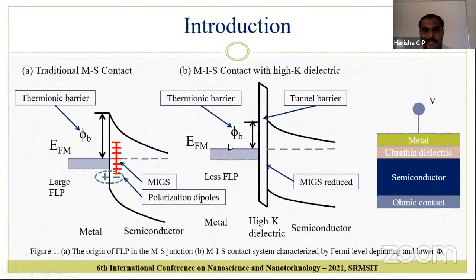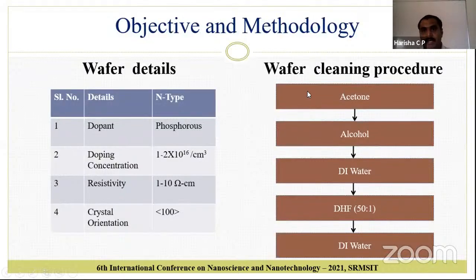But one thing is very important at this stage: the thickness of the thin dielectric layer is very important, because the thickness should not be too high. If the thickness of the intermediate layer is too high, it is going to produce a tunneling barrier. So our experimentation was conducted with 1 nanometer, 2 nanometer, and 3 nanometer titanium oxide and hafnium oxide, and also with a bilayer structure. We have taken an N-type silicon with phosphorus doping. Before the actual experimentation, we cleaned the surface with acetone, alcohol, and DI water, and the native oxide was removed by DHF cleaning, diluted hydrofluoric acid cleaning, followed by DI.